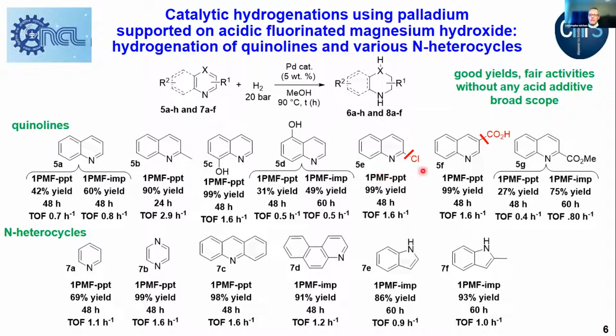We had drawbacks regarding the scope, with dechlorination proceeding along the hydrogenation of the heterocycles, same for the decarboxylation of such substrates. However, the esters could be selectively hydrogenated without reduction of the ester function, as shown here. Other heterocycles could be hydrogenated, and it is very important to say that this was done without any acid additive.